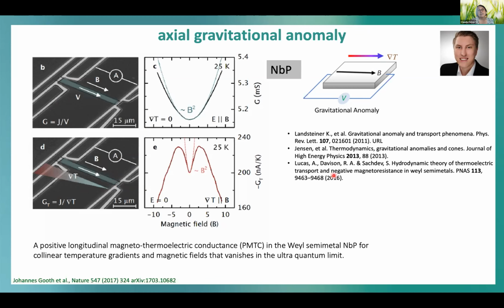And the prediction here from theory, from Subir Sachdev and co-workers, was that you should see a B-squared behavior at low fields, and this should turn around and go to zero at higher field. And this was indeed exactly what we saw when we applied a thermal gradient at this nanoribbon.